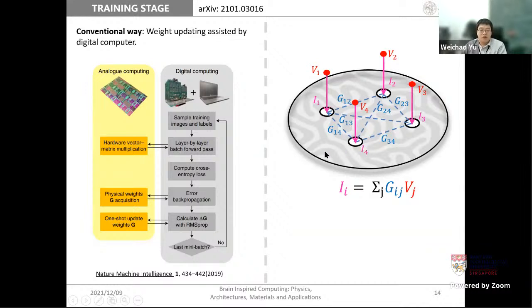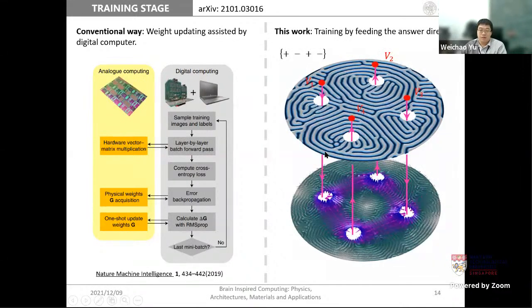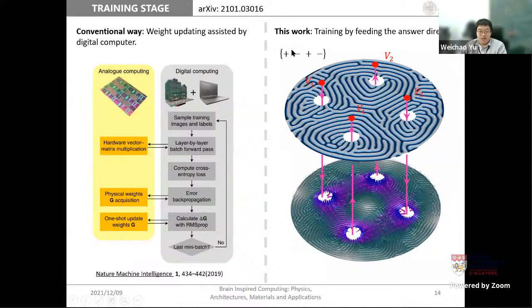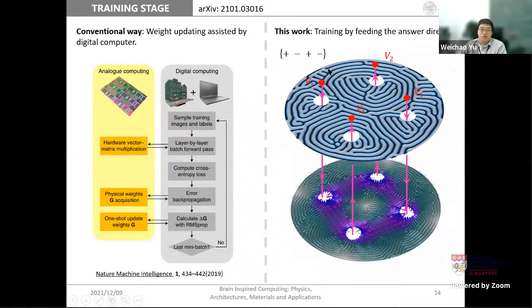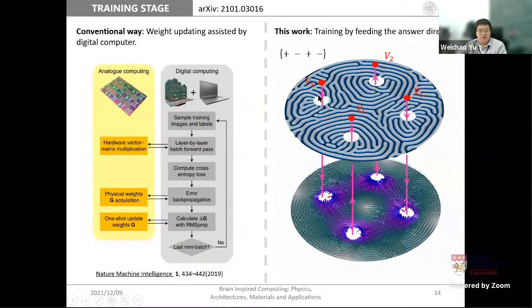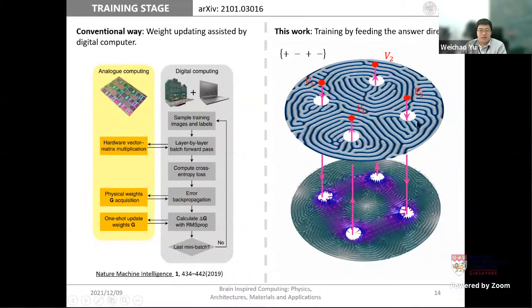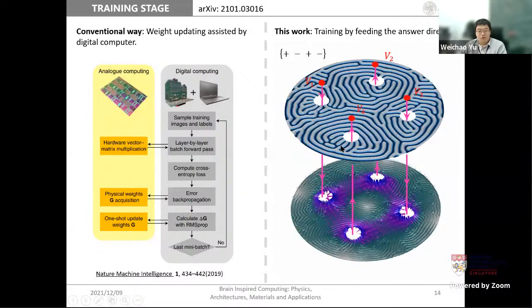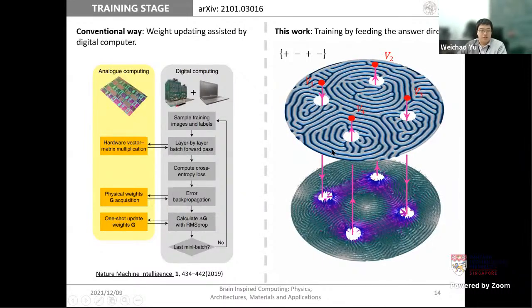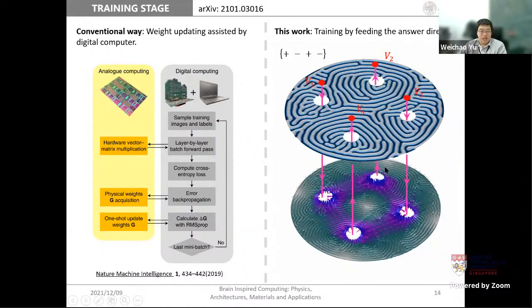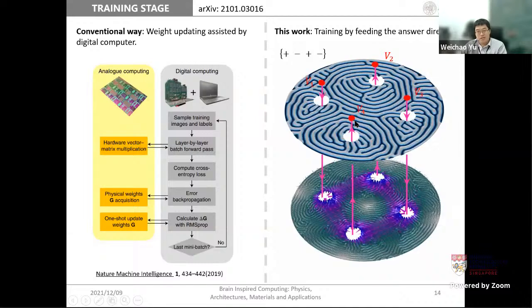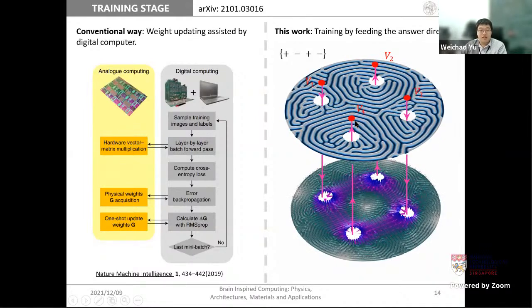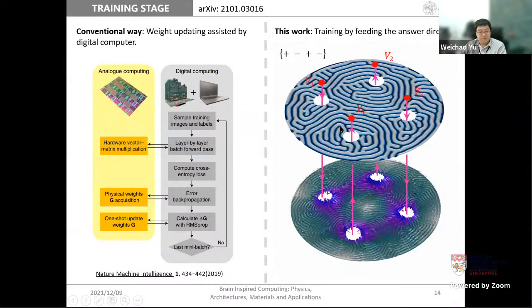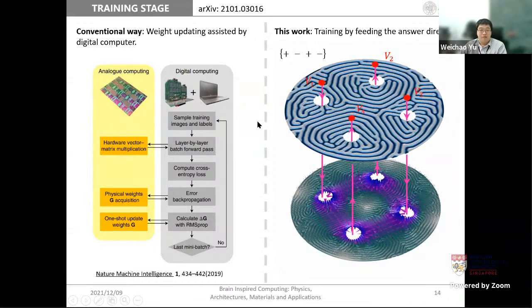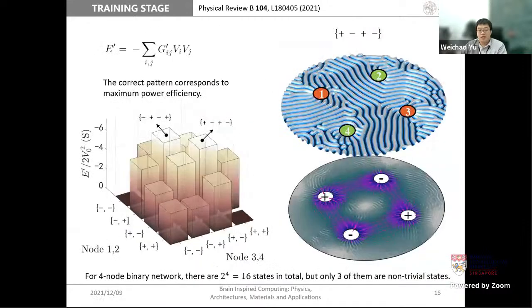For example, now we are going to store a 4-pixel binary pattern. Let's say plus minus, plus minus. What we do is to apply the corresponding voltage on each electrode in a clockwise way. According to Kirchhoff's law, the voltage difference will generate currents flowing through the magnetic film, and the currents will drive the magnetic textures because there is spin transfer torque. After a sufficiently long time, the texture will finally become stable, and we say that the training is finished.